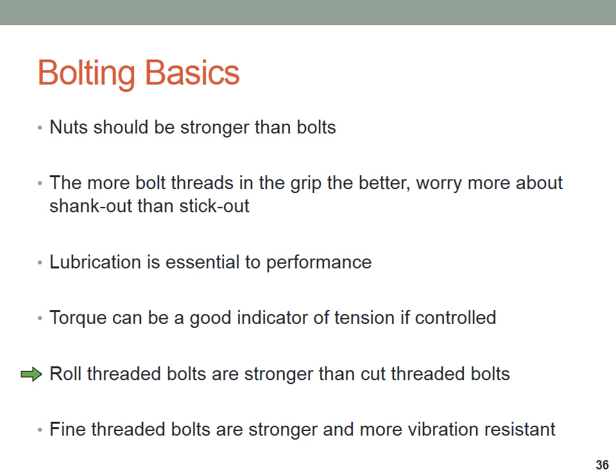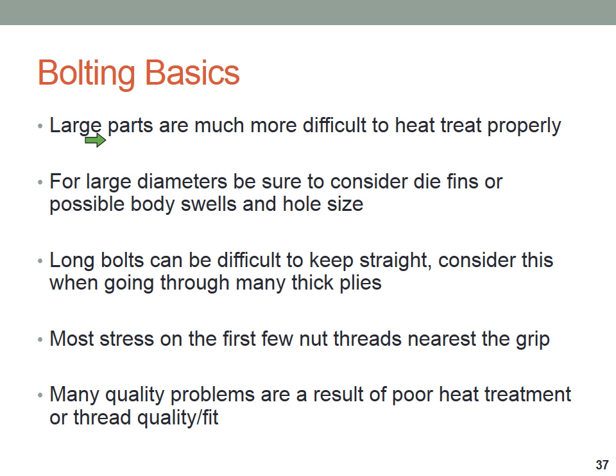Rolled threaded bolts are typically stronger than cut threaded bolts. Fine threaded bolts are stronger and more vibration resistant than coarse threaded bolts. Large diameter parts are more difficult to heat treat properly. When we get up around 1.5 inch, 2 inch diameter, it's sort of like cooking a really thick steak. It's hard to properly heat treat a part because it cannot quench at the same rate, and so the core of the part tends to be much softer in hardness. The outside of the part tends to be much higher in hardness, and that makes it difficult for the part to sort of uniformly distribute load. And we tend to get a little bit nervous as parts get larger.